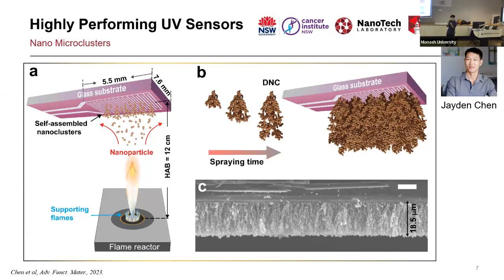But then the challenge is sometimes when they are too small, they merge with each other and you end up with, again, very welded, agglomerated nanoparticles. It is possible to solve that problem, but then you wouldn't end up with, I would say, 5 micrometers of film in a minute. You have to do it slowly. You have to spray maybe for 20 minutes in order to create the same film, but then you control that, you prevent the particles from joining.